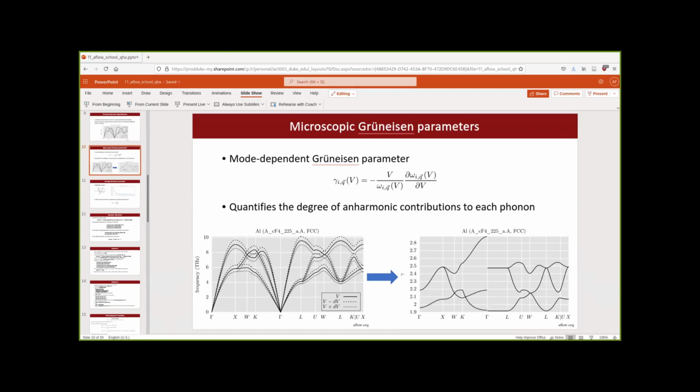Interesting. So it's a bit similar to the case that Dr. Asters had with non-analytic contributions. So the Grüneisen parameter near the gamma point actually depends on the path by which you approach it, and at gamma itself, you cannot really define it.